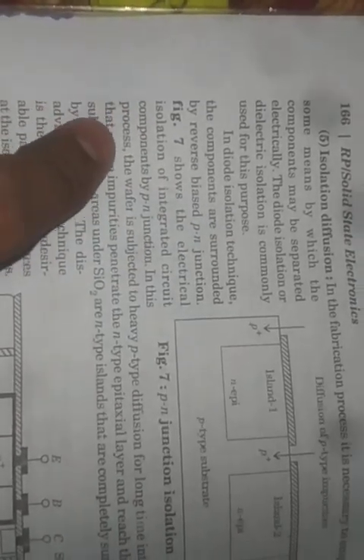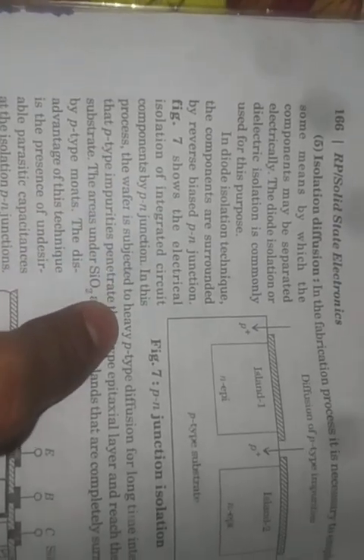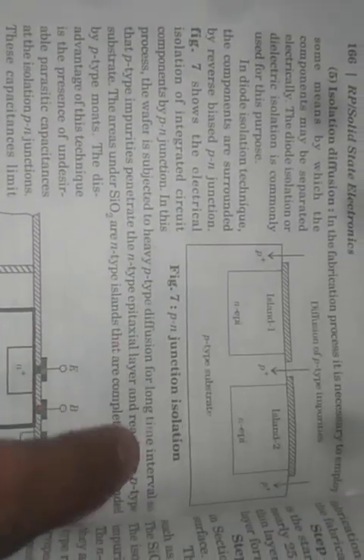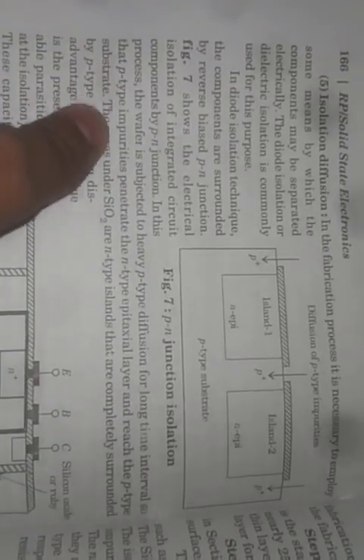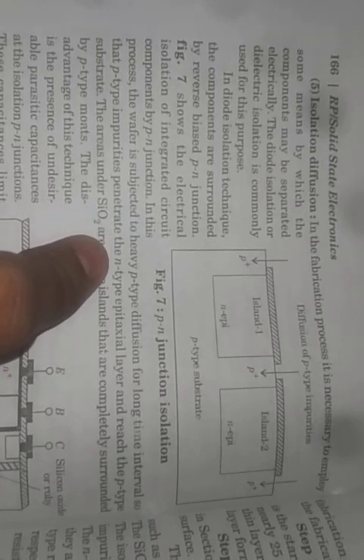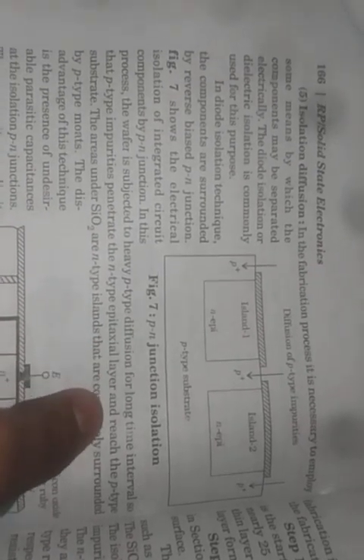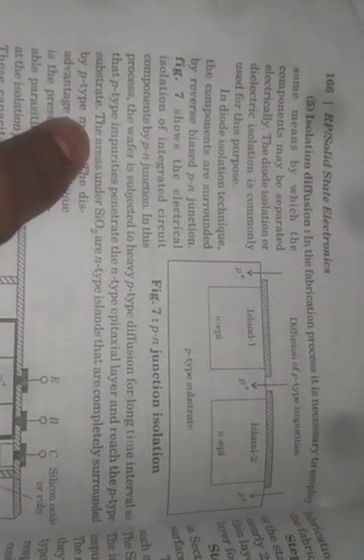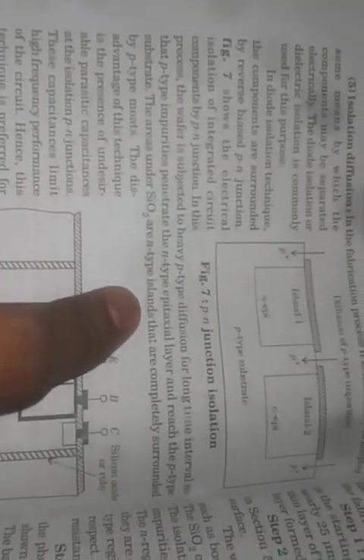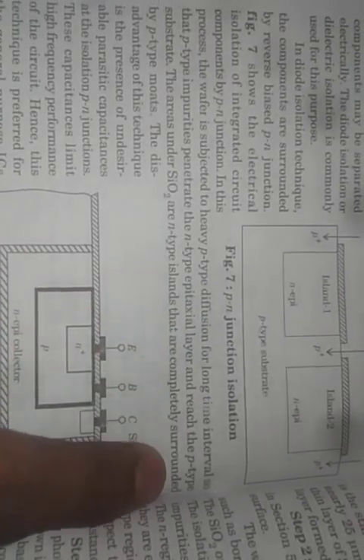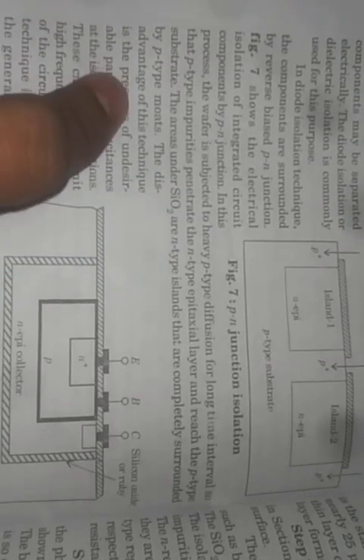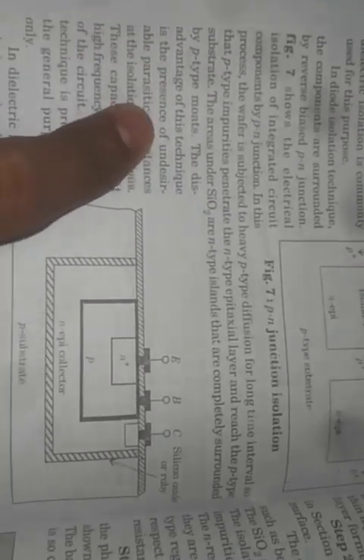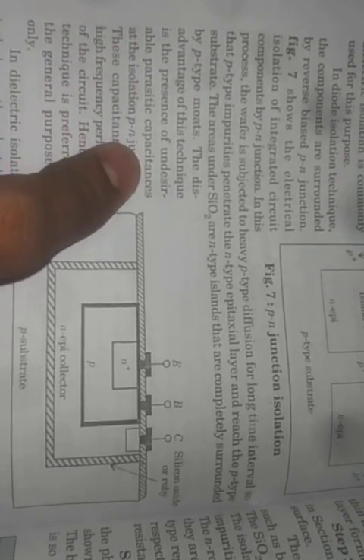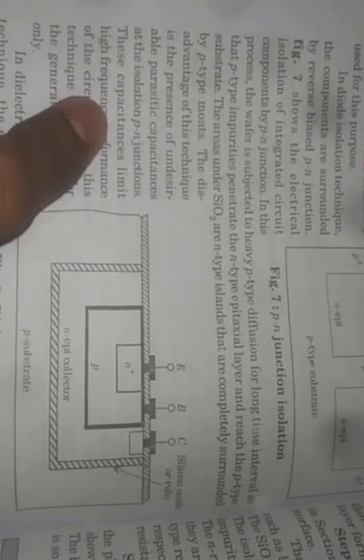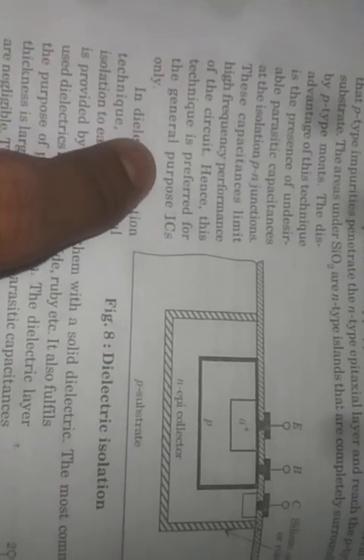In this process, the wafer is subjected to heavy p-type diffusion for long time intervals so that p-type impurities penetrate the n-type epitaxial layer and reach the p-type substrate. The area under SiO2 becomes an n-type island completely surrounded by p-type regions. The disadvantage of this technique is the presence of undesirable parasitic capacitances at the isolation p-n junction. These capacitances limit the high frequency performance of the circuit, hence this technique is preferred for general purpose ICs only.